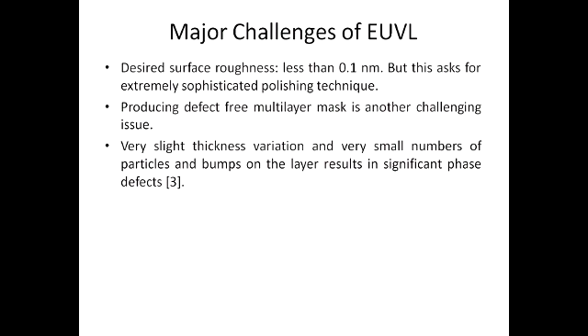So what are the challenges? My desired surface roughness would be less than 0.1 nanometer, but it needs an extremely sophisticated technique for polishing the surface, and it's very hard if we go below the 13.5 nanometer wavelength. And of course, if you use a multi-layer mask, then it would be another challenge to produce a defect-free mask. Another point is that very slight thickness variation and very small numbers of particles can make the layer rough, so if we use several masks, then on top of the bottom layer, it will be really rough, and our process might be damaged.